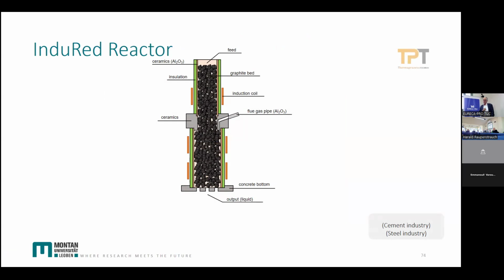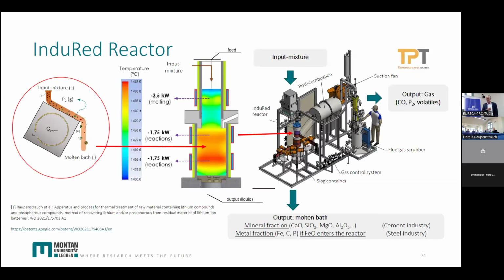So we created a reactor which is similar on the one hand side, but completely different on the other hand side. This reactor consists of graphite particles, and these graphite particles are heated with induction coils. In this case, we have 3 induction coils, and this gives us the possibility to create the desired temperature profile in flow direction and across the flow direction. That means we have a temperature profile in the flow direction, and an even, smooth temperature profile across the flow direction. That means we can define the reaction conditions very precisely. And then we can decide where the flue gas pipe should be to get out the phosphorus from there. And that's an example for the temperature profiles you see simulated in this case.